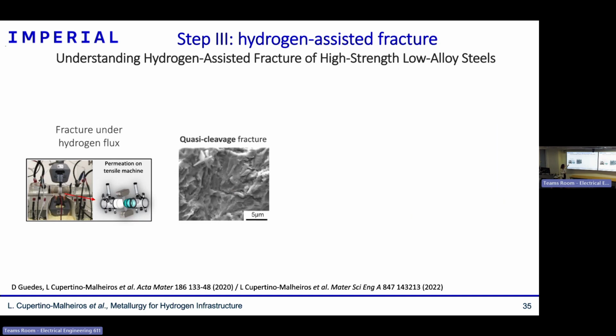Okay, but now looking at the test on the hydrogen flux, when you look at the fracture surface, you already see it completely changed. It's nothing like the one with the voids. This morphology is called quasi-cleavage. It illustrates that it's more brittle.